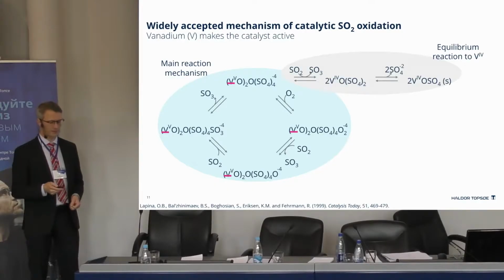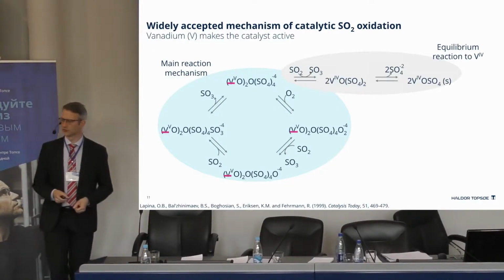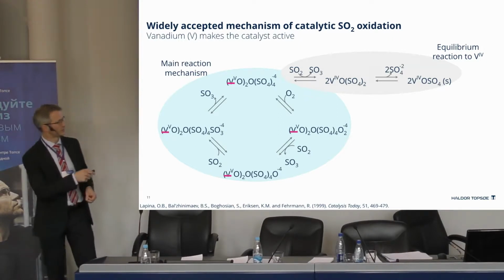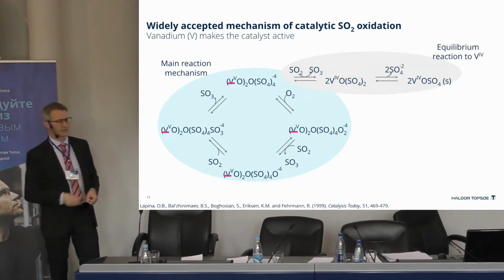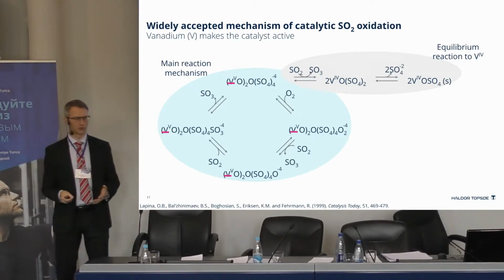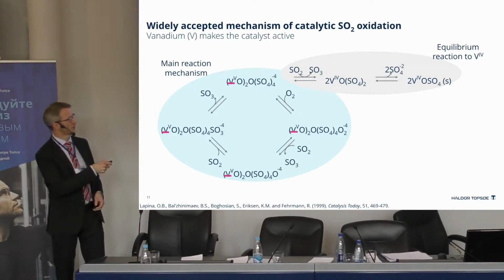However, not all vanadium in this catalyst is in oxidation state 5. So depending on the conditions, some of the vanadium is reduced to vanadium 4, shown by this branch, especially at high partial pressure of SO2 and low temperature. A lot of the vanadium will be reduced to vanadium 4, and some of it can precipitate out as solid vanadium 4 compounds.